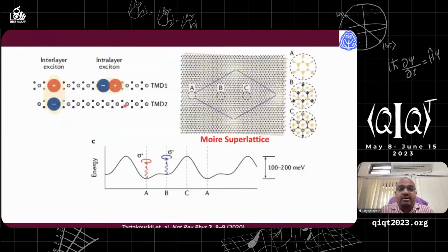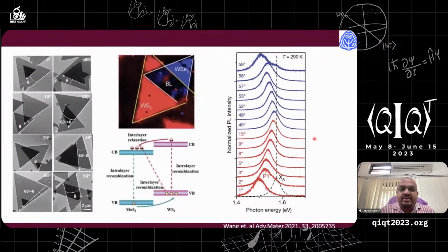Now, coming to this twistronic type of material, here I have shown two different materials stacked together at a different angle, and you see the periodicity that emerges. If you consider the high symmetry points A, B and C, and how the atoms are arranged, they are highlighted here. You can see the atomic arrangement evolving from A to B to C, then back to A. As the atomic arrangement is periodic and changing, one expects a lot of change in the electronic and transport properties as well. So this type of material is very interesting. And here I have shown that just by tuning the twist angle, one can tune the band gap of the material.